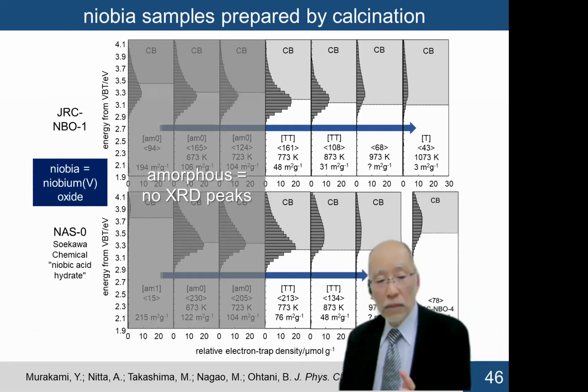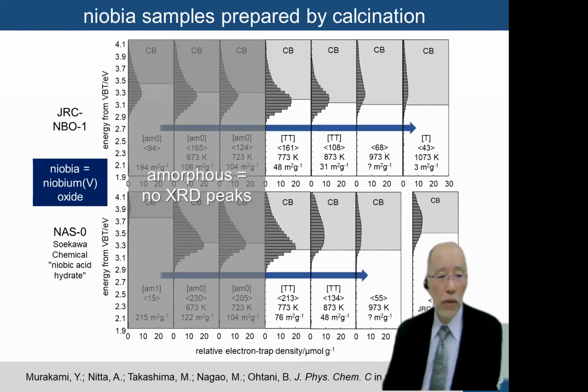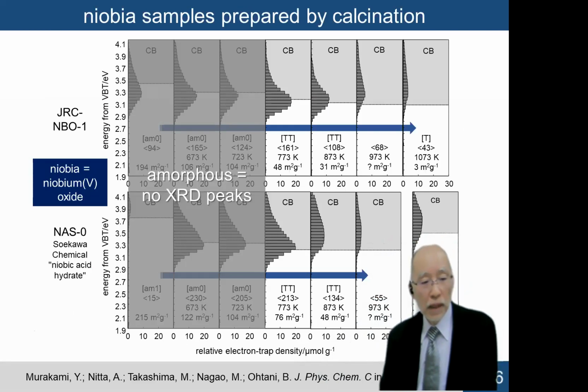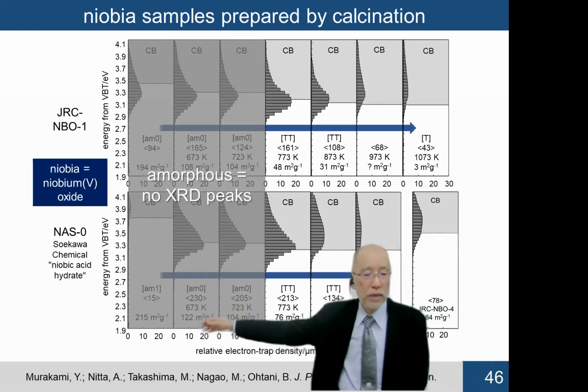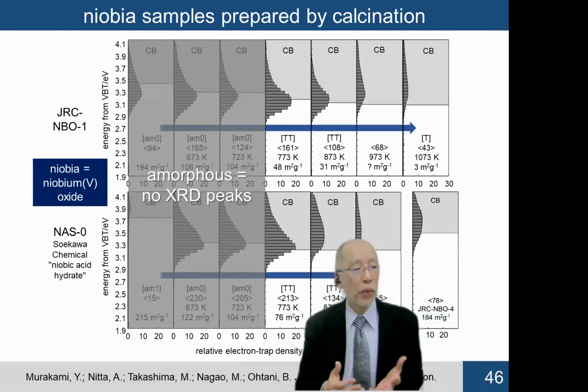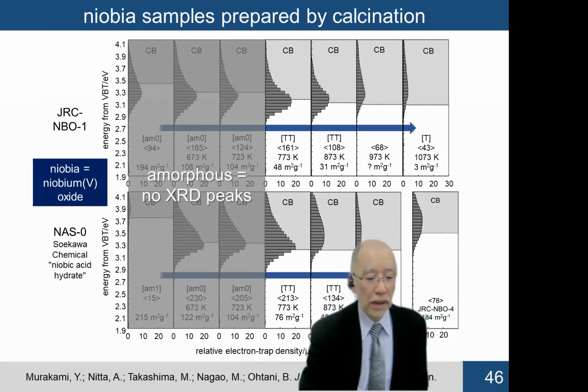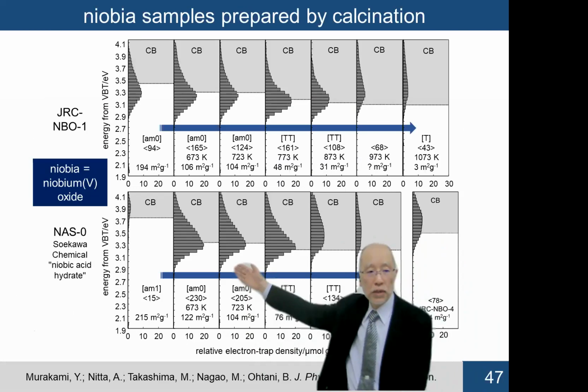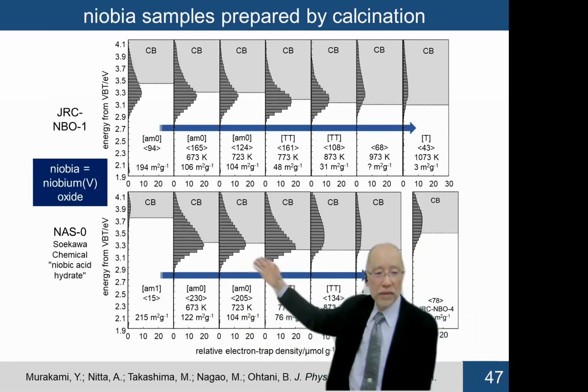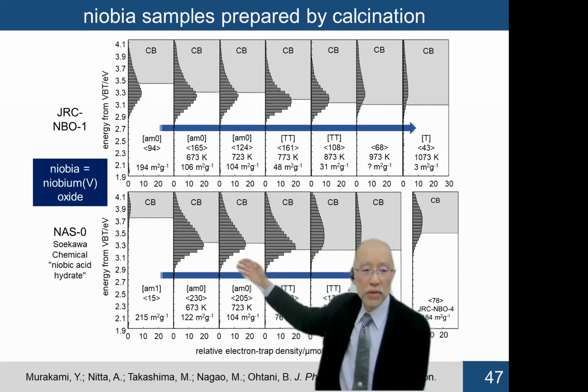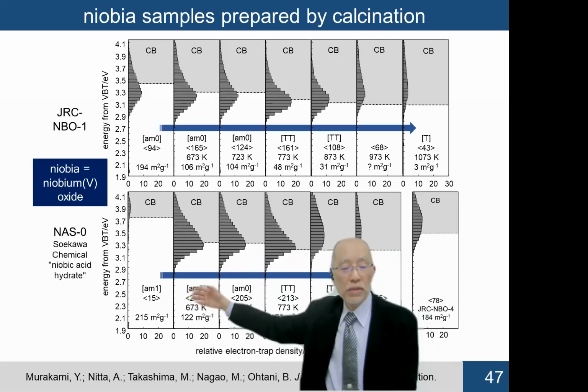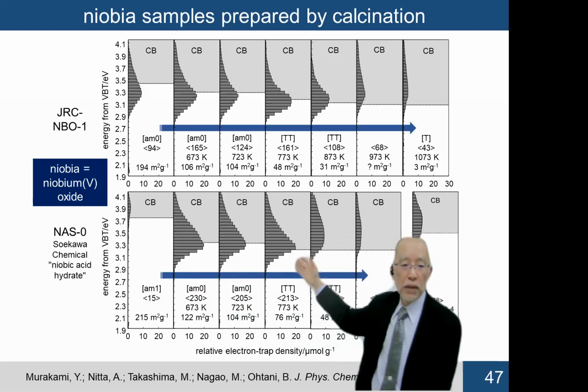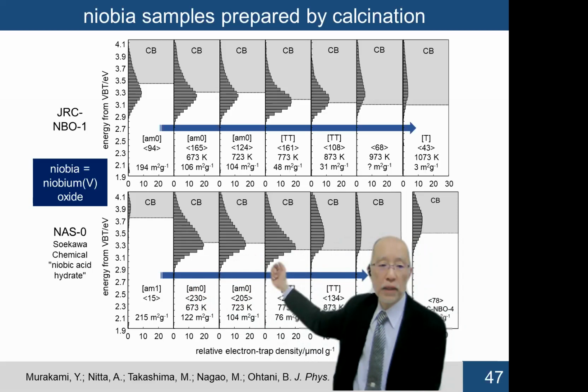And as I told you, for commercial titania, amorphous material can also be analyzed. This is the result for niobium oxide, Nb2O5. Those gray parts, 6 samples, are completely amorphous, meaning no XRD peaks are given. But we can see the ERDT pattern like this, and it is not so different from crystalline materials. So the ERDT pattern tells the surface structure. Even if the bulk structure is amorphous, non-crystalline, or partly contains a crystalline part, the surface structure is not so different.